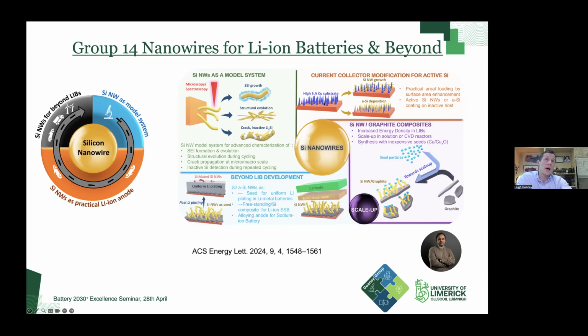Some of the opportunities here are around modifying the current collector, for example. So increasing the surface area of the current collector and then growing your nanowires up here, as we have tried some approaches in the University of Limerick in the past. And we've also used these nanowire architectures as hosts for amorphous silicon deposition. So this is the example that I will show in the next couple of slides.